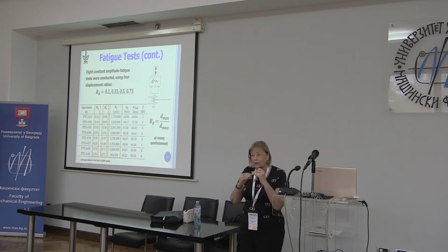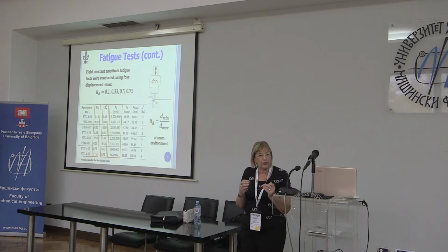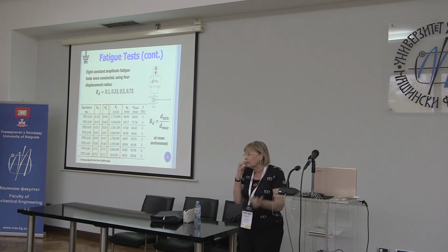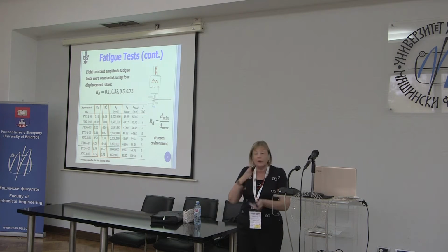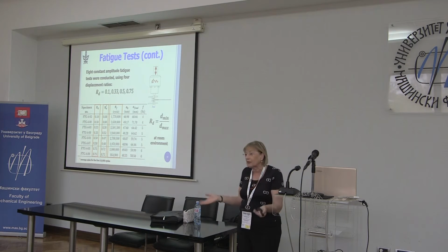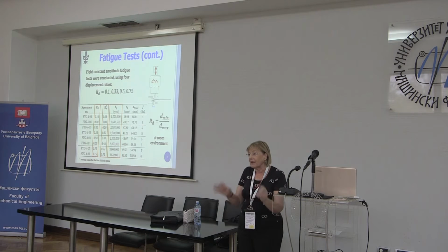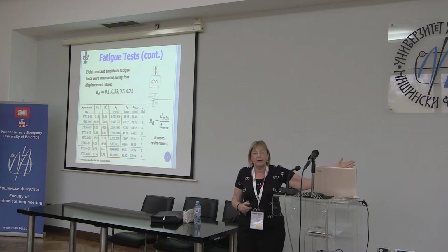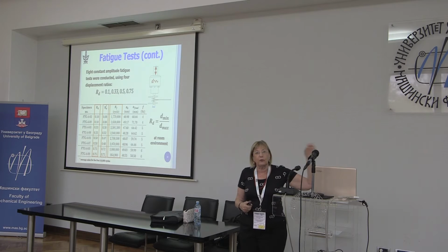Well, when you put it in, you don't put it in exactly the same place. It moves. The displacements are so small that it moves, and so you get a lot of scatter in the results. But I was loath to leave the machine on for 24 hours a day. Oh, what's going to happen in the middle of the night? Well, it runs in the middle of the night and everything's fine. You come in the morning and we take crack lengths, we take pictures.